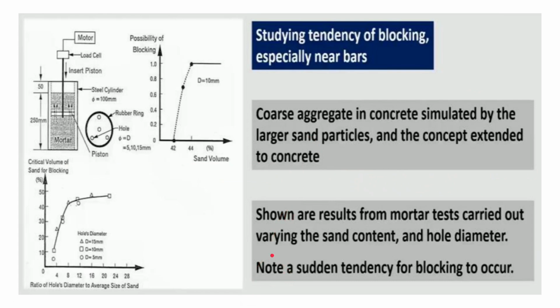So experiments have been done basically using some mortars. Here the results are shown for various mortar tests carried out varying the sand content and hole diameter. It has been observed that there is a sudden tendency for blocking to occur, as you can see. After the sand volume increases from say 42%, there is a possibility of blocking which becomes 100% after it reaches 44%, in case of mortar.